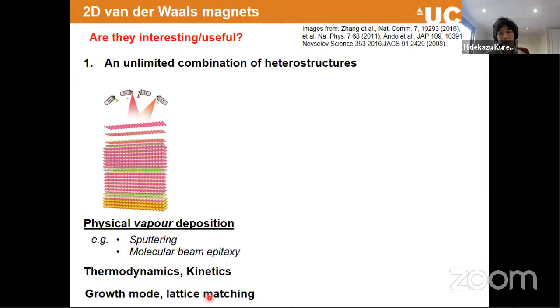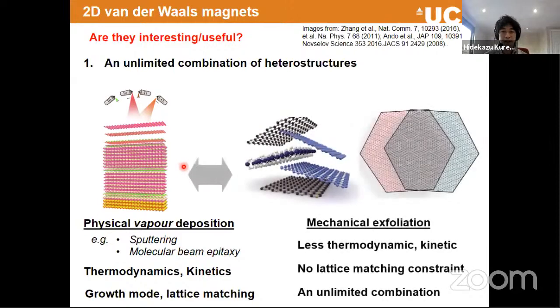And also, if you want to grow epitaxial films, one of the things we have to worry about is the lattice matching, so that we can make lattices on top of each other. So that's a typical thing we can think of. But when we look at the van der Waals growth technique, for example, a popular one is mechanical exfoliation. Then what we can think is that the unit of the growing material is not just atoms or dimers, but thermodynamically ordered films or layers, and they can be put on top of each other. So when you put them on top of each other, there's less constraint from thermodynamics and kinetics, and therefore we can artificially create different heterostructures.